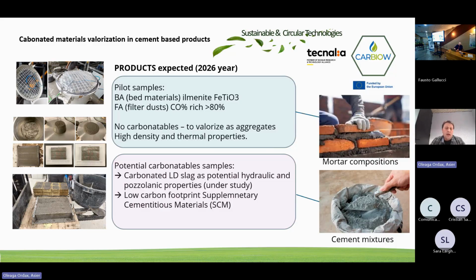In this case, the valorization of this product is contemplated as aggregates for mortars, but we keep working with the LD slag because it can be used in these oxy conversion processes. If in the future it is more available and reduces the cost of processing and conditioning, and you demonstrate that you can carbonate these wastes, you can valorize them in lower carbon footprint materials like cement mixtures.